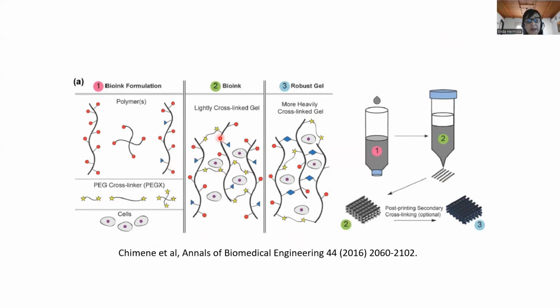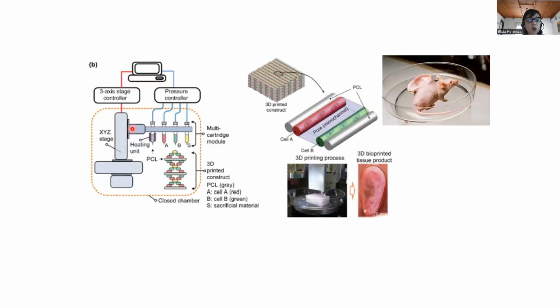Let's say at the beginning, just one part of cross-linking, and then after being printed another, as I mentioned, with the gelation and then the cross-linking with calcium, also including more than 2 different kinds of inks. Here you have even one of the cartridges that has a heating unit for thermoplastics. Not only hydrogels, but we can also use certain kinds of thermoplastics. In this case it was PCL, a thermoplastic that fuses at around 60 degrees centigrade. You can print really complex structures with more than one type of cells. So this is a very wide area of bioprinting. I wish to listen to you, and thank you very much for your attention.